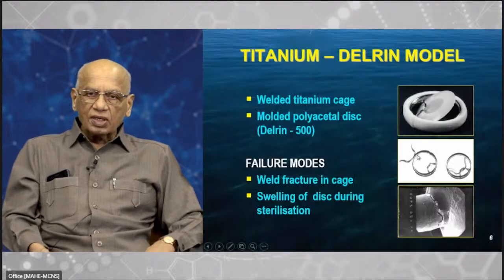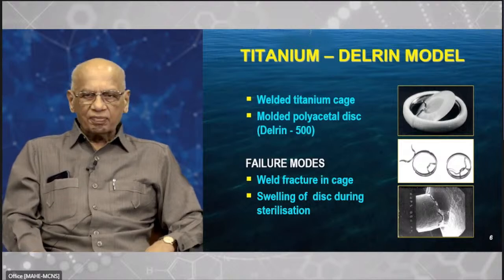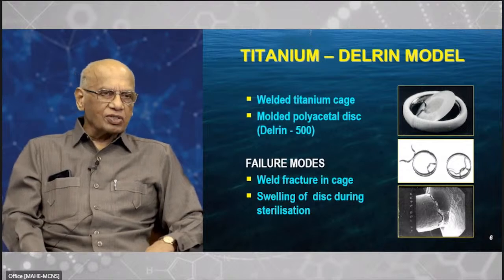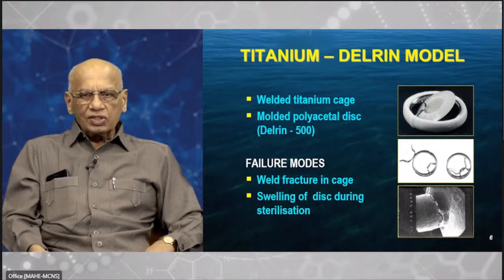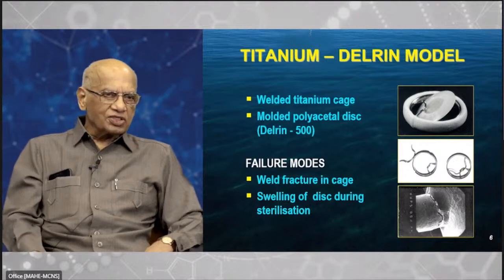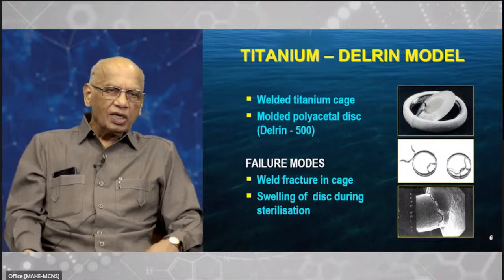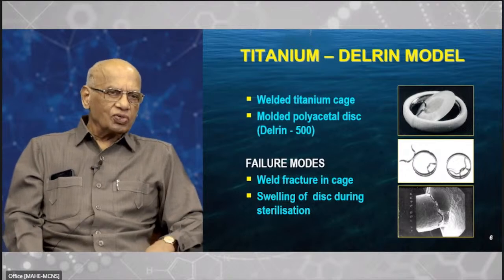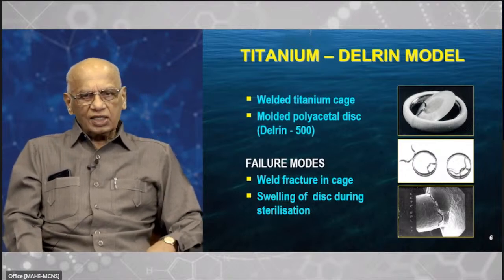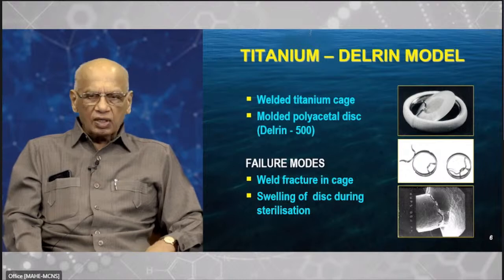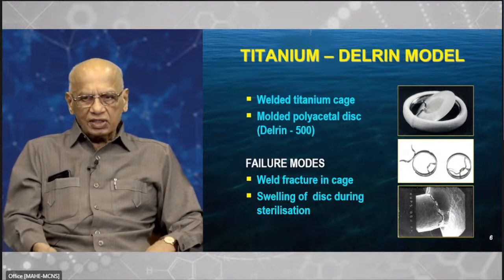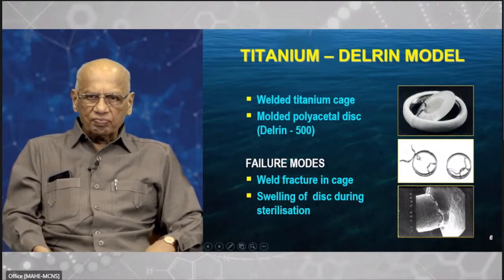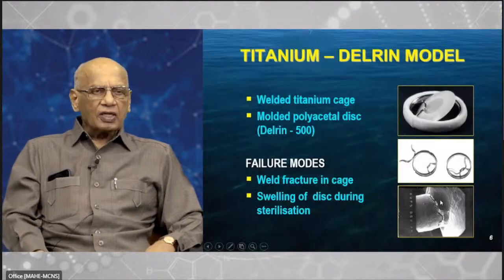You can see that major strut simply fractured at the joint where it was welded. It cracked. That was the end of the model. And when this metal fracture happened, we had no facility to test it. We didn't know how to deal with it. So we took it to the National Aeronautical Laboratory in Bangalore. They did a study for us, and this is one of the pictures they took. You can see the crack very well there.